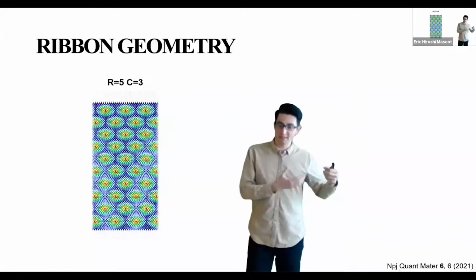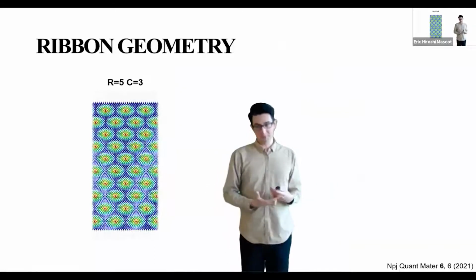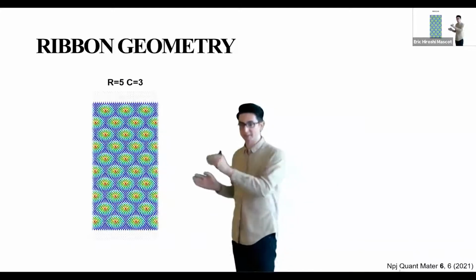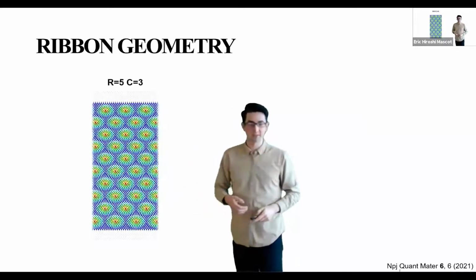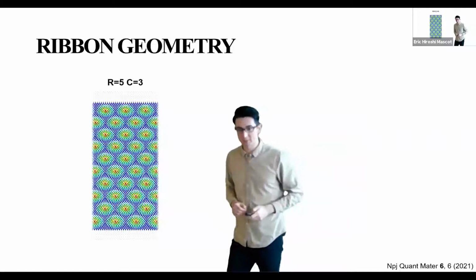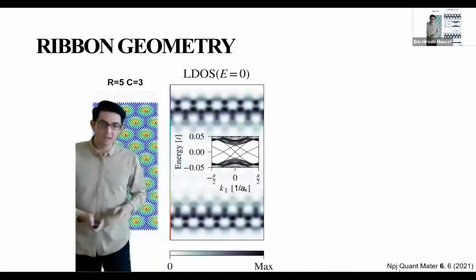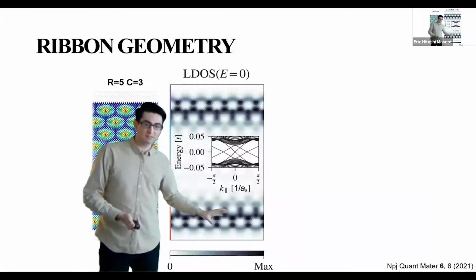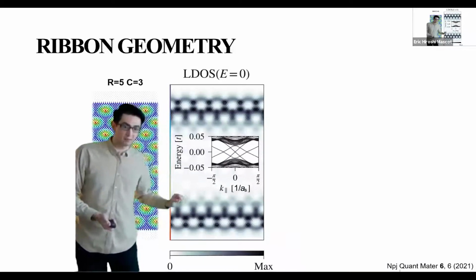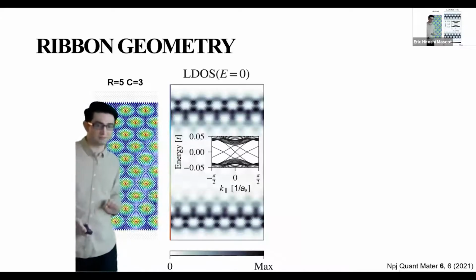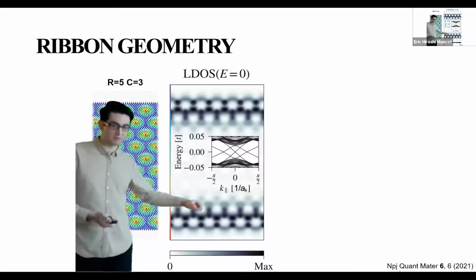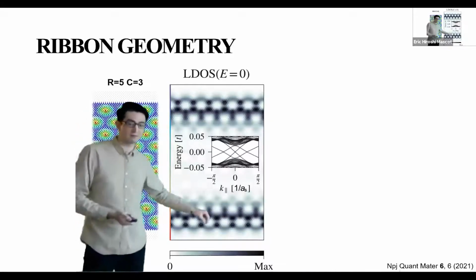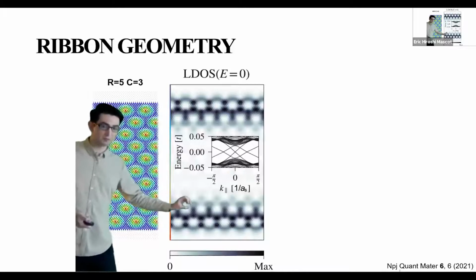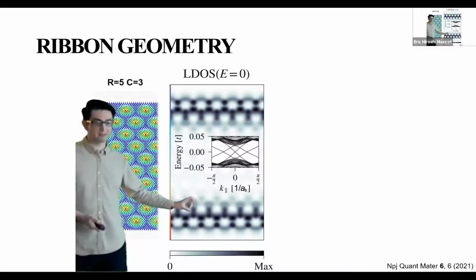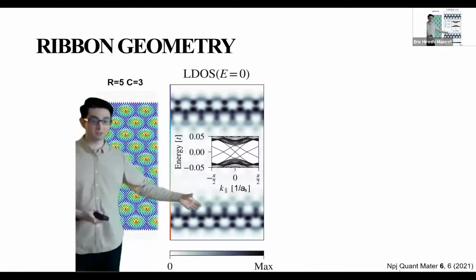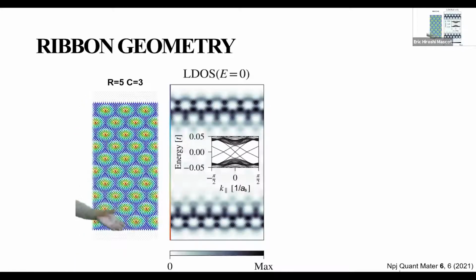And now we want to study the signature of the Majorana zero modes. So we look at a ribbon geometry again. We put this magnetic ribbon on top of a superconducting substrate, and we have these skyrmions. And if we look at the local density of states, we get at zero energy this edge state. But if you notice, it's only focused on the corners of the skyrmion. So the edge mode kind of rotates around these skyrmions. And this would be an electronic signature in the scanning tunneling spectroscopy, but it also shows a signature of the magnetic structure.